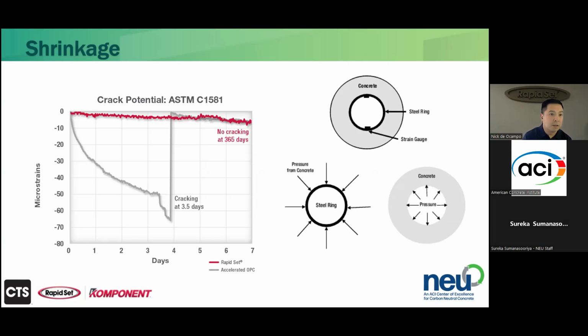So on the chart here on the left, we can follow the accelerated Portland cement, the gray line, all the way down to 3 days, where you have 50 microstrains of shrinkage. It continues to shrink between 3 and 4 days to about 60, 65 microstrains, at which point the stress is too much and it cracks.